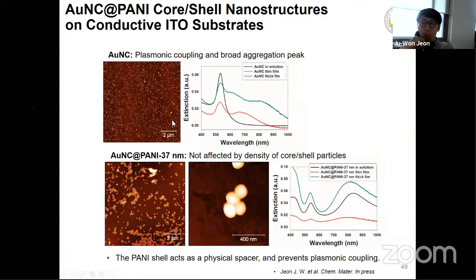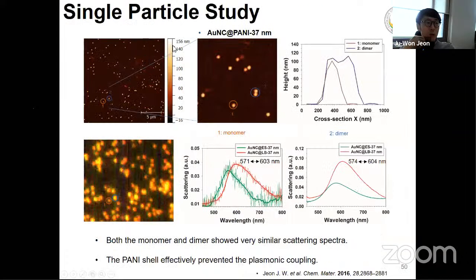So these are the SEM images of the gold nanocube and gold nanocube polyaniline core/shell structures. And we also performed the single particle studies for the core/shell nanostructures. So for the AFM, we found one particle, just a monomer. And this number 2 is two particles contacting each other. And these are the height profiles of the one monomer and a dimer.